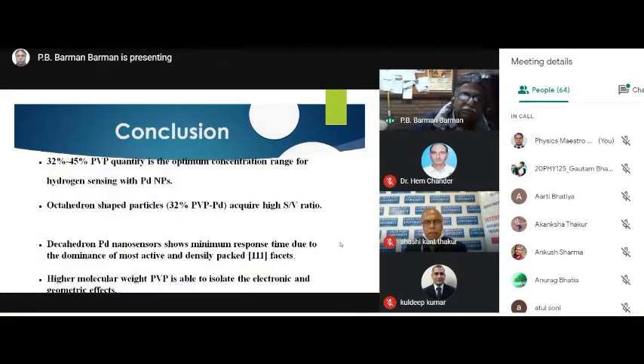So the conclusion is that 32 to 45% PVP quantity is the optimum concentration range for the hydrogen sensor. This is with respect to the present study, and we are working on it. The octahedron shape of particles, and not only the shape but also the 111 facet, plays an important role at 32% PVP palladium, since it acquires a high surface to volume ratio.